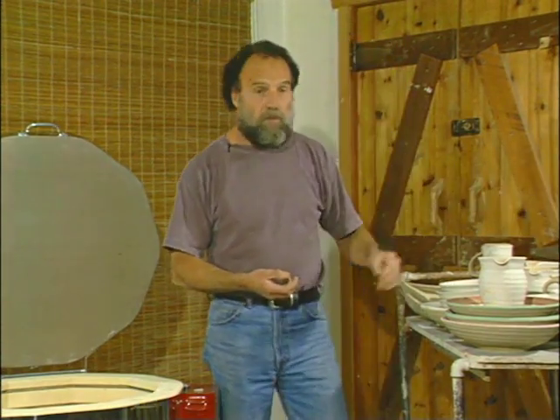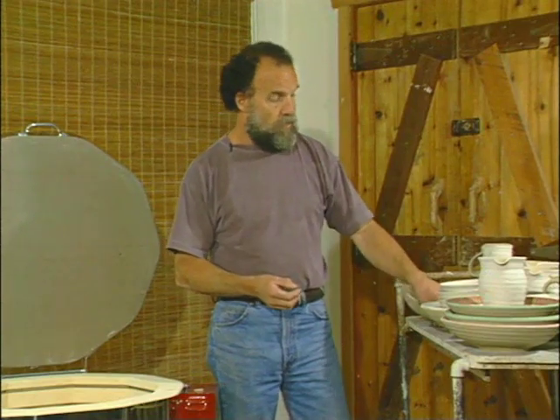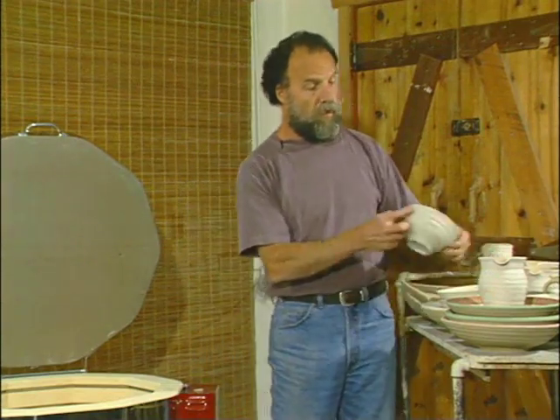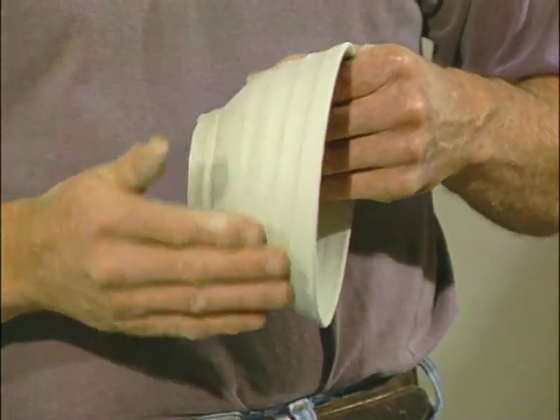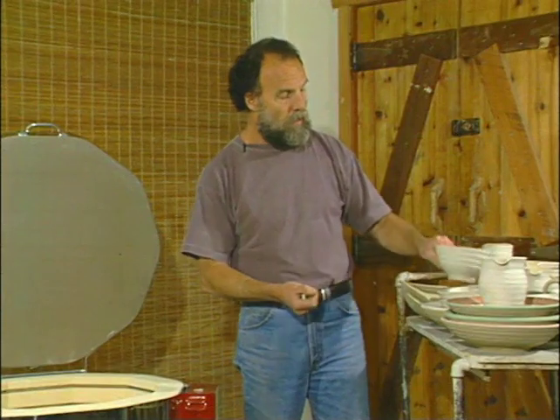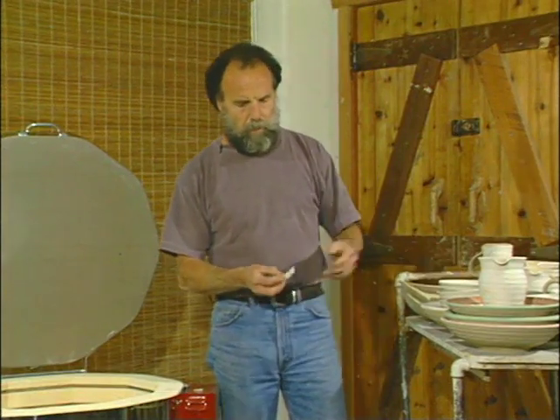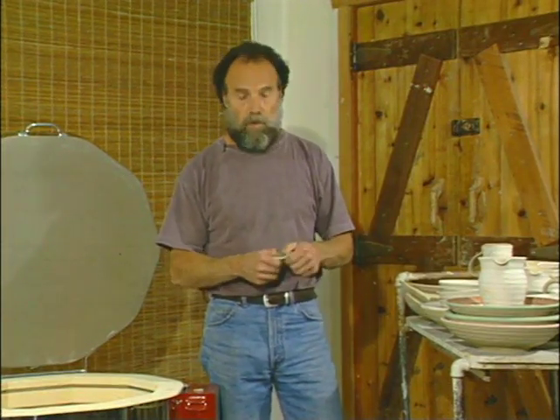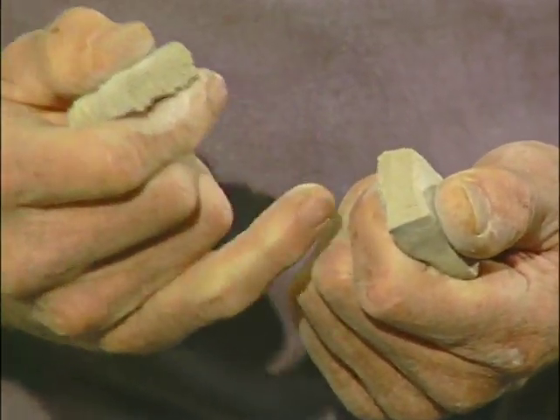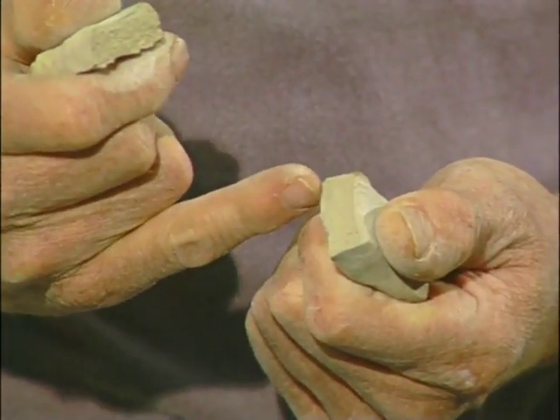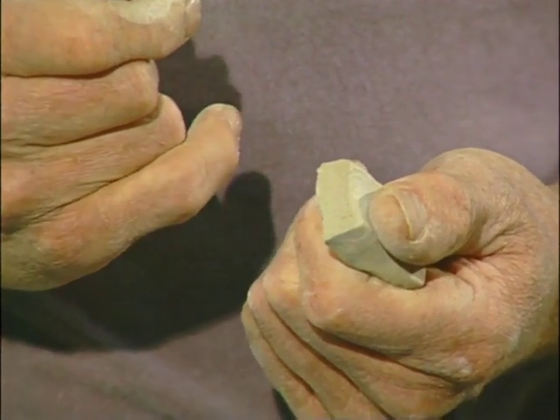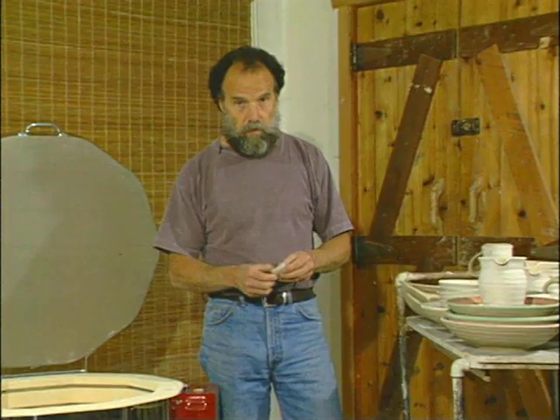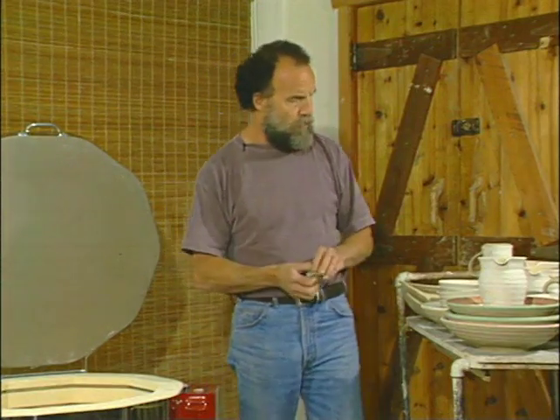Now there are several ways of testing whether the pots are dry enough to bisque. One of them is simply that they first of all must have this uniformly chalky looking appearance all over. Second, if you make a little sample piece at the same time that you're making your pots, you've always got the option of breaking it open prior to bisquing to make sure that the coloration is the same right the way through and that the piece is indeed dried through.